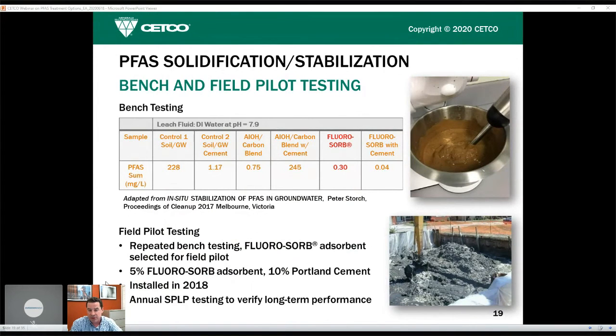The other material that he used, the gibbsite carbon blend, was somewhat effective in the soil by itself. However, when you added cement, you saw a 2 order of magnitude increase in the leaching, which was kind of interesting. It kind of suggests that the cement has a negative interaction with this particular type of treatment. Whereas with our FLUORO-SORB product, we saw the lowest leaching, around 0.3 ppm. And with adding cement, we saw a reduction by an order of magnitude. So this study kind of demonstrated that adding cement and FLUORO-SORB works together to help solve the problem. And this was installed in 2018 and is undergoing annual SPLP leaching studies.